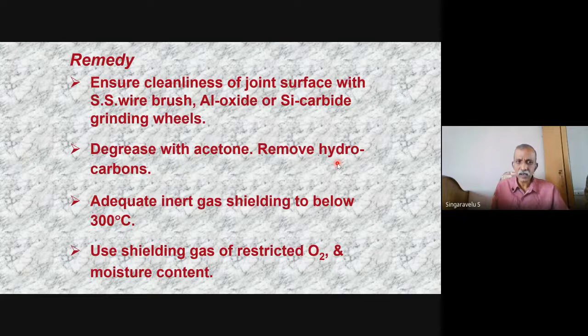Remove all the hydrocarbon. Use adequate inert gas shielding up to 300 degrees centigrade of the deposited weld metal. Most important thing, the shielding gas should be restricted in oxygen and moisture content. Ultra pure argon, 99.999 purity category. That much purity gas cylinder has to be used for the argon.